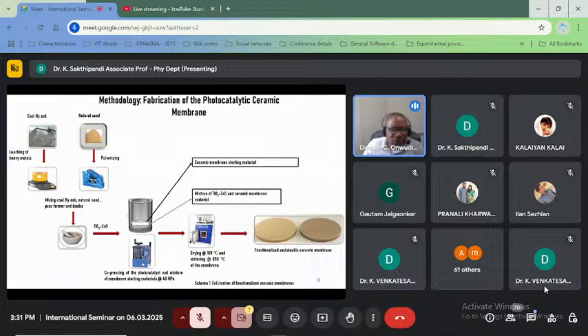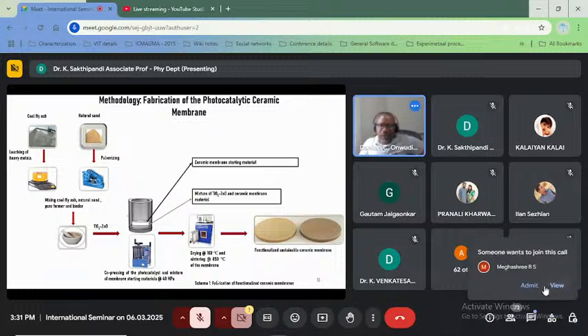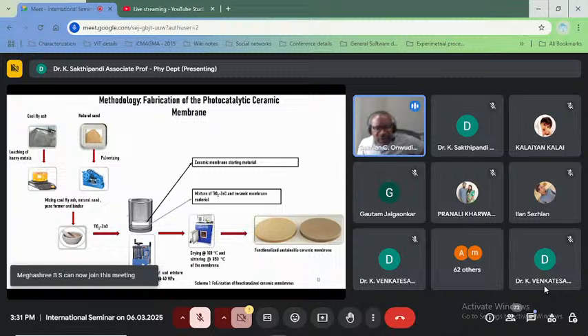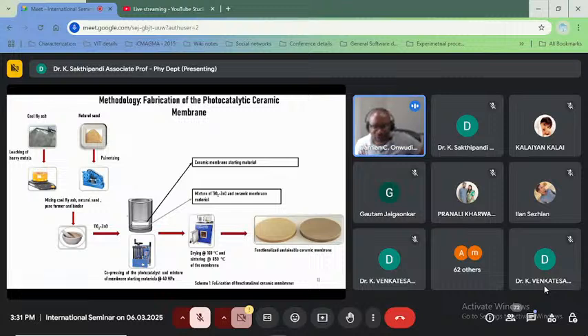Then we introduce natural sand to strengthen it. Then we add some pore making material and some binders to hold them together. Then we introduce it into a pulverizer and pulverize it into fine materials, and then use a pressing machine to press it down to form these ceramic membranes. These ceramic membranes then come in different sizes, different strengths, different pore dimensions. We can then use nanomaterial, depending on the choice of nanomaterial, to coat the surface of the ceramic membrane.